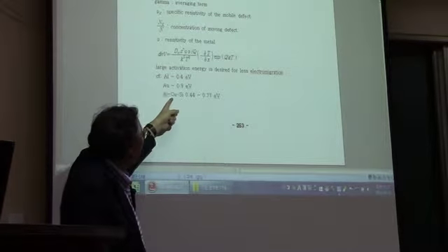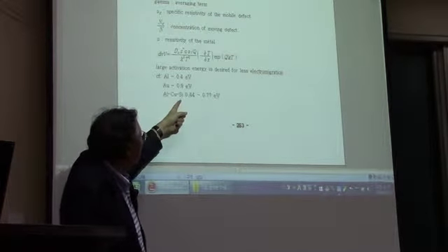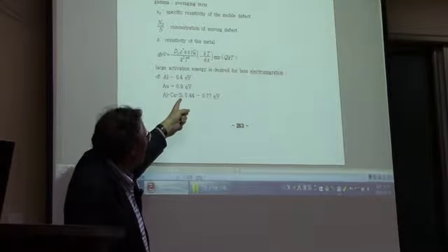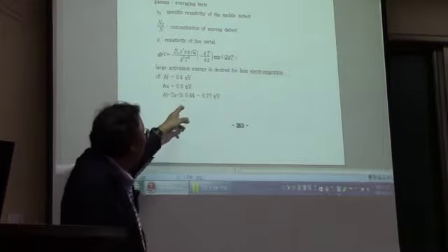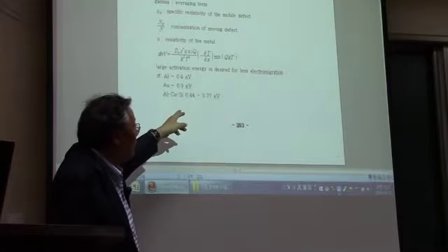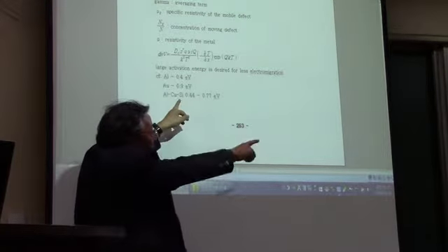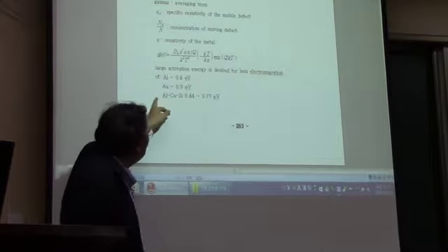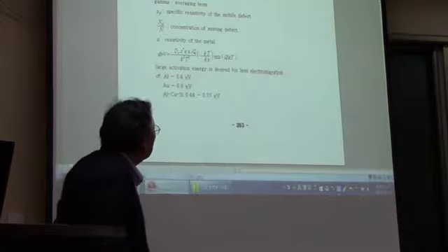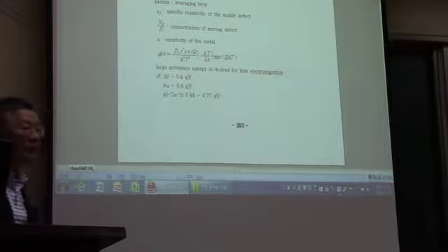And if you add copper and you add silicon, it's just for prevention of junction spiking, as we discussed in number 1 there, then this is the typical metal line, and its activation energy is 0.44 to 0.77.